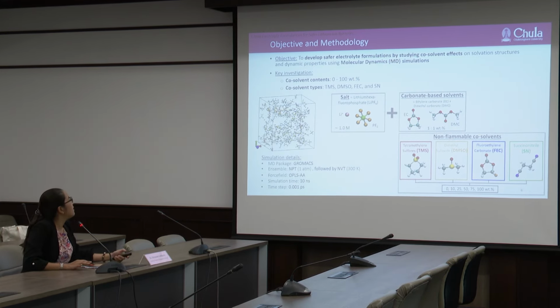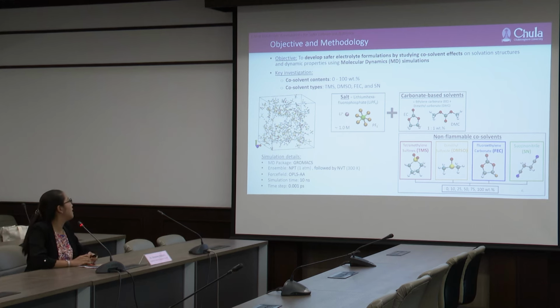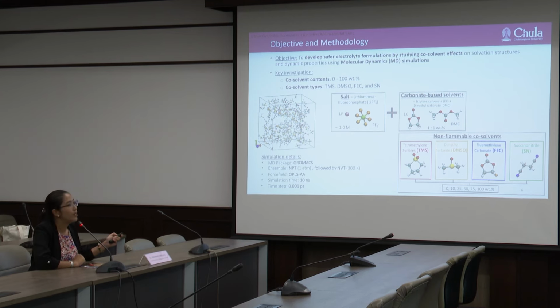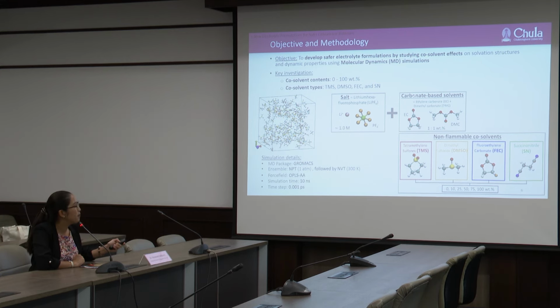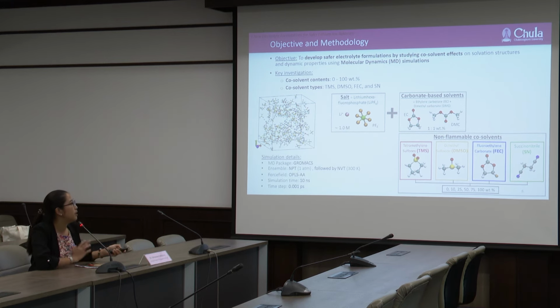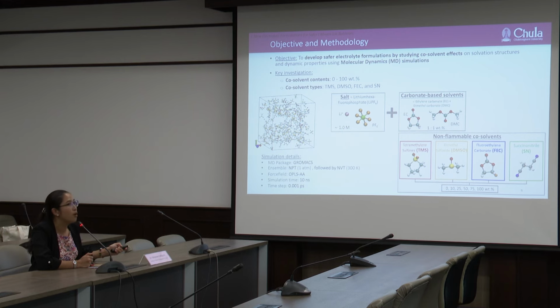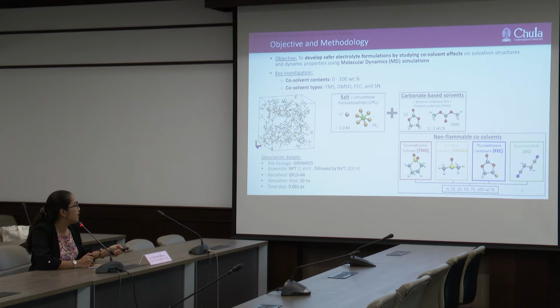So, the objective of this work is to develop safer electrolyte formulations by studying co-solvent effects on the solvation structure and dynamics property using molecular dynamics simulations. There are 2 key investigations. First is co-solvent contents and another is co-solvent types. We make a simulation box. The lithium salt is LiPF6, the common salt mixed with carbonate-based solvent. And we use non-flammable co-solvents. There are 4 types of co-solvent that are going to be mixed in the system. First is tetramethylene sulfone or sulfolane or TMS, dimethyl sulfoxide or DMSO, fluoroethylene carbonate or FEC, and succinonitrile or SN.